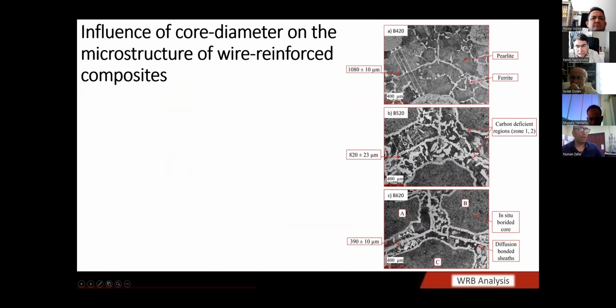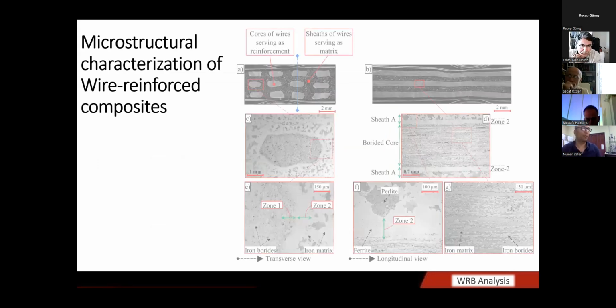Increasing the wire core diameter results in a smaller section of steel, a smaller amount of steel content in the wire reinforced composite. Here you see a steel content of 1 millimeter, which reduces to 0.5 millimeter when you increase the core diameter of the wires. So now you have a hard core material and a softer steel matrix, and all the debris of the material removed during the wear test is expected to embed in these materials. Because you have control on the cross section, you can also change the wear behavior of the wires if you use this material for an application in which wear is the primary objective.